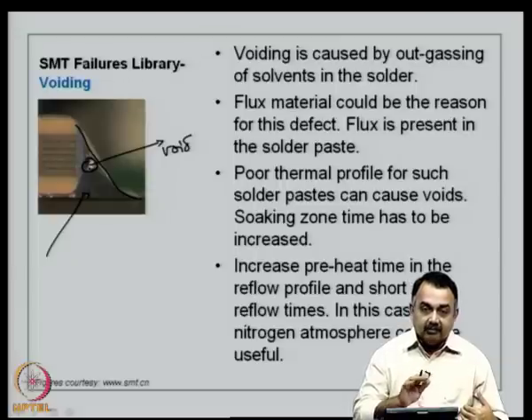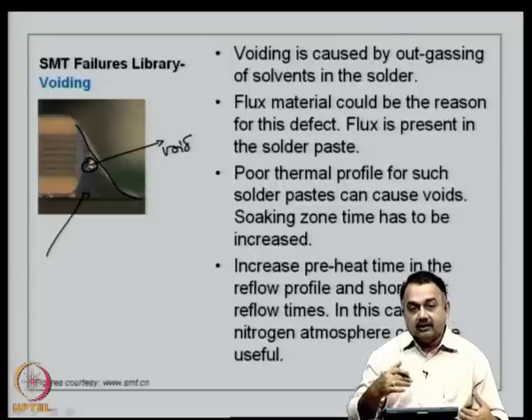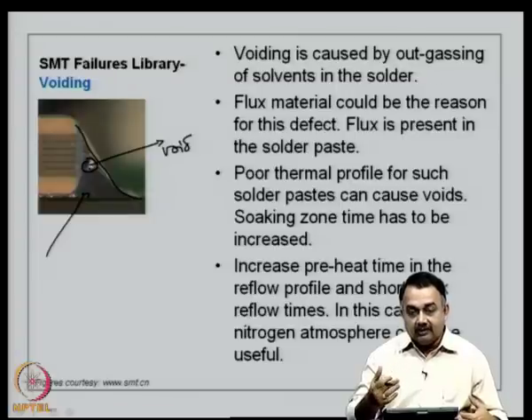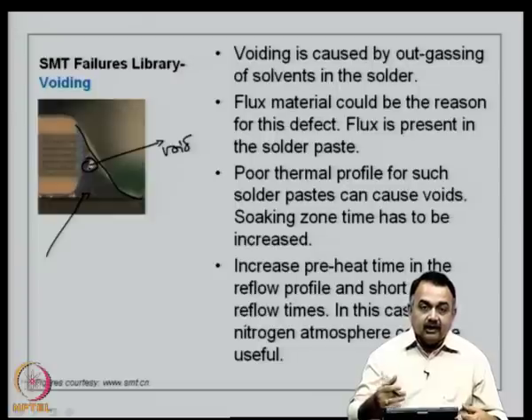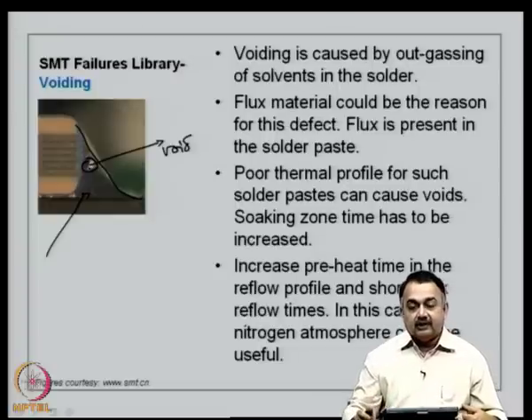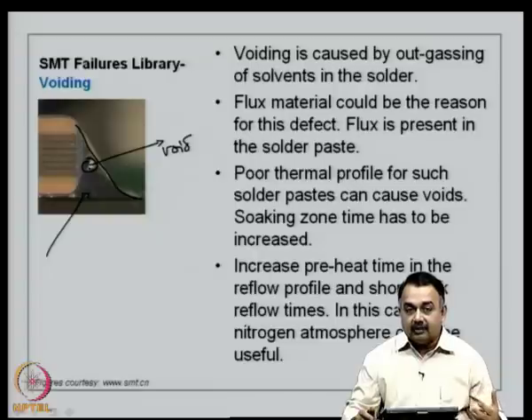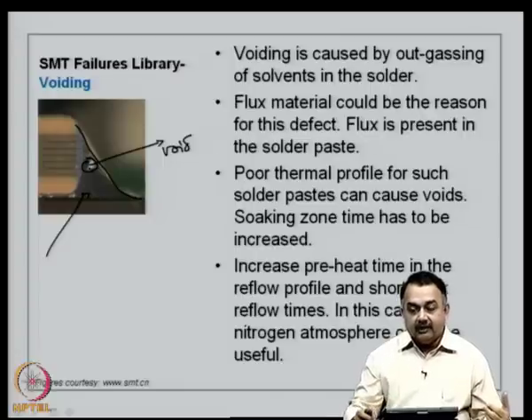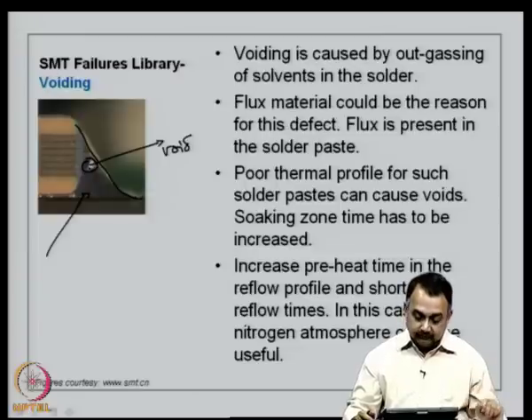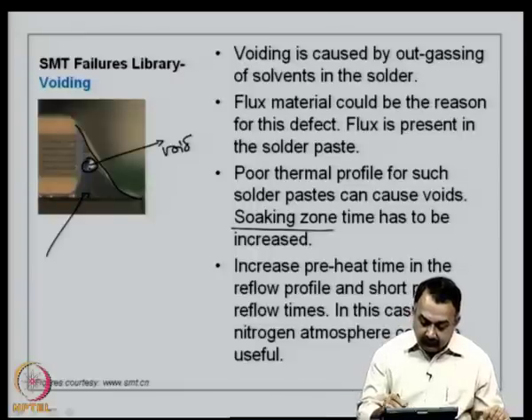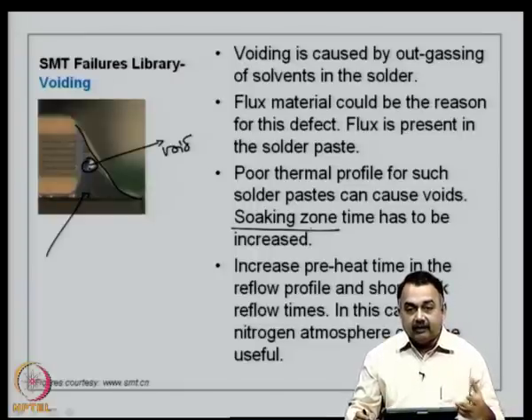You have to look at the substrate material Tg, you have to look at what solvents are being used, what binder is used and what flux material is used, and accordingly slowly remove these solvents or evaporate the solvents very gradually. If you give a very high heating rate in the thermal profile that you have generated, then the solvents could just bubble out, okay, and the resulting outgassing could create voids. So, the soaking zone, as we call it, in the thermal profiling has to be increased.